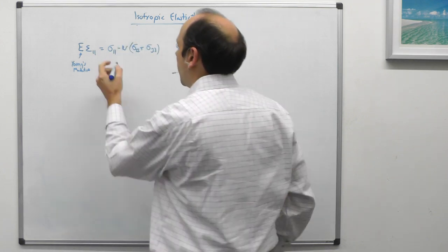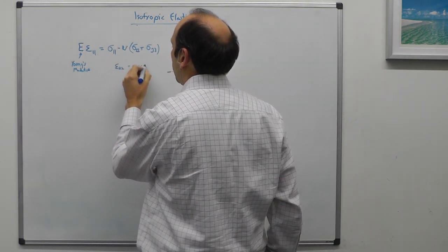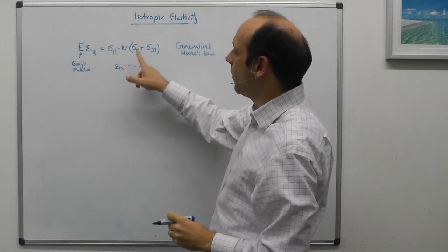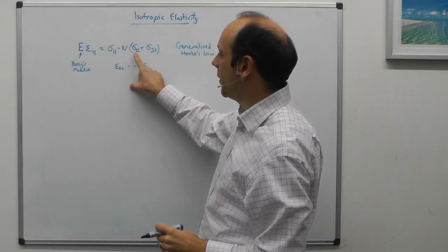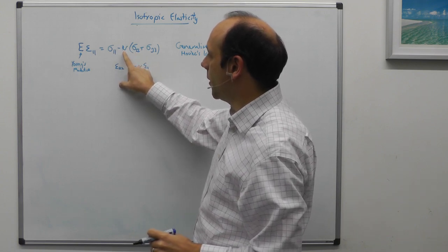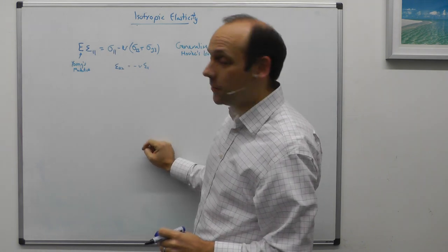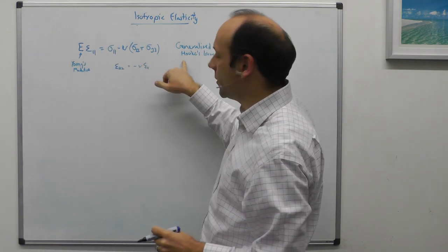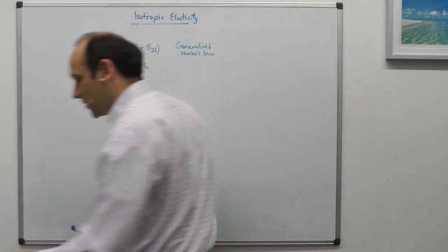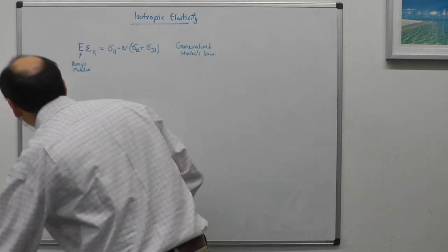And then you've said that strain 2-2, or the strain in a second direction, is equal to minus mu times strain 1-1. And when you add on a stress in the two direction, that then gives you a strain in the one direction, which is related to E, and also multiplied by mu. So this is the generalized version for when you have normal stresses in three different directions. And the shears in this, for the normal strains at least, don't come into it.